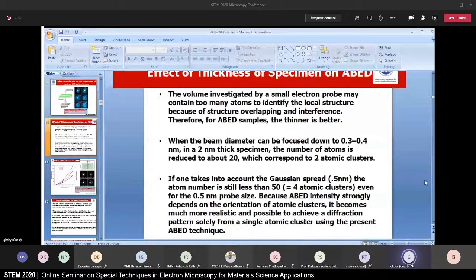If you have a beam which is 3 or 4 angstrom in diameter, and a thickness of 2 nanometer, then you will be examining about 20 atoms. That means 2 clusters. A very good situation. A 2 nanometer thick specimen is not impossible to get. And if you have a slightly broader beam, 5 angstrom in diameter, and after Gaussian spread inside the specimen, you will be examining about 50 atoms, so 4 clusters. It's still a manageable situation, because not all the clusters will be suitably oriented. So there are 3 things: thickness of the specimen, size of the beam, and orientation of the cluster, which will give rise to important information.